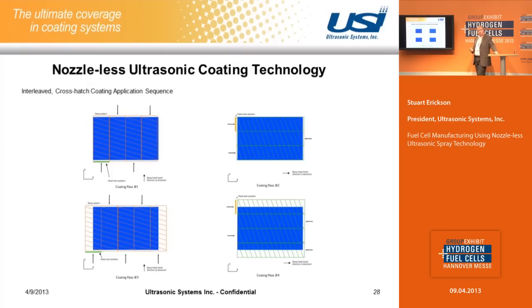Another way that we're going to show you for fuel cell application is to use the crosshatched interleaved method. Since we have a rectangular pattern, we find that in order to make a uniform pattern, you can spray in one direction and coat your substrate. You can rotate the head 90 degrees and spray the other direction, rotate it back, and spray another set of patterns that are halfway in between these patterns, rotate it, and put another set halfway in between these patterns. And that would be a typical layer that we would apply for a fuel cell.